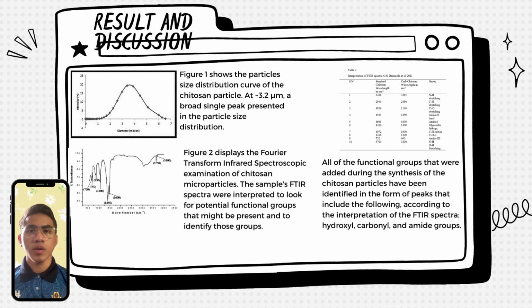For the first one, figure 1 shows the particle size distribution of Chitosan particles. At 3.2 micron diameter, a broad single peak is present in the particle size distribution. This shows the maximum size of the Chitosan particle.